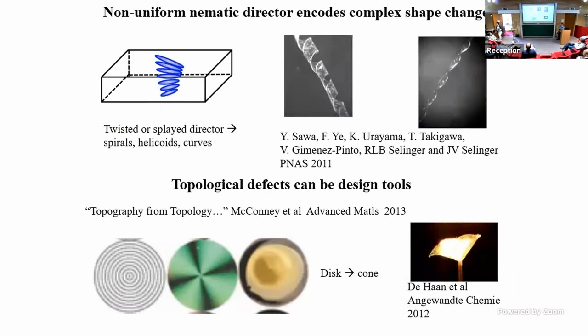What kind of patterning can we do? The simplest thing to do is to put a twist in the director, and all your liquid crystal devices, the original liquid crystal display, which by the way, the inventor was at Kent State, uses a twisted geometry for the director. So in that case, you can actually rub two pieces of glass, one east-west, one north-south, put a nematic liquid crystal in between, in this case also with monomers, cross-linking agents, and then a little chiral dopant to make sure, because when you have a 90-degree twist, you can twist clockwise or counterclockwise. So a chiral dopant is a chiral additive that encourages the system to twist in a particular direction so you don't get any defects. And then you can shine UV light through one of the pieces of glass or both sides if you prefer, and cross-link that twist in there.